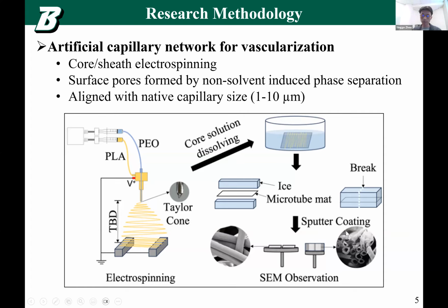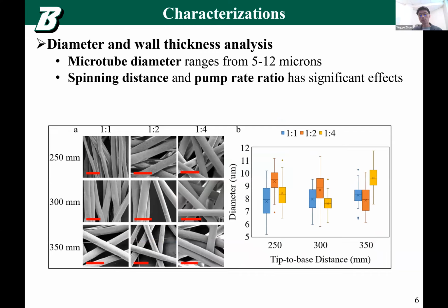Then we proved that we got tubes instead of fibers, and those tubes are really nice tubes, as you can see in the SEM. So our next step is to investigate how we can use the electrospinning parameters to control, for example, the diameter and the wall thickness of the tubes. And we can also see there's some surface pores on the tubes.